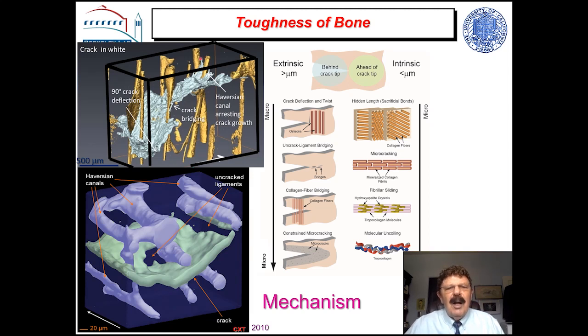These are the osteonal structures or Haversian canals, and you see the crack deflects and twists as it encounters those structures. If we look in the other orientation, you can see there are the osteons again. This white region here is the crack. There's the head of the crack, and these dark blue regions are these uncracked ligaments, which are these little regions between the microcracks which act to bridge the material.